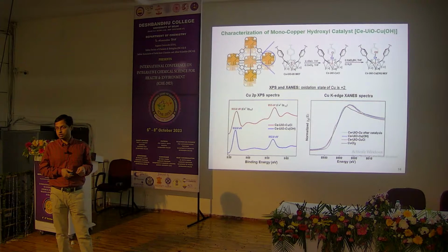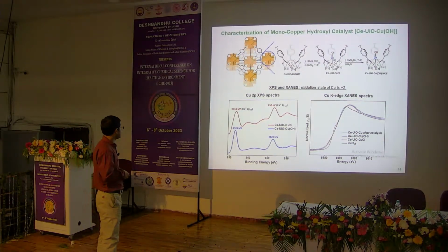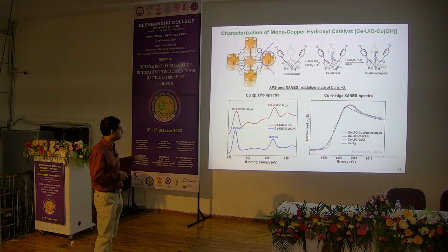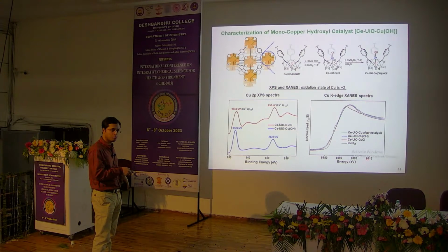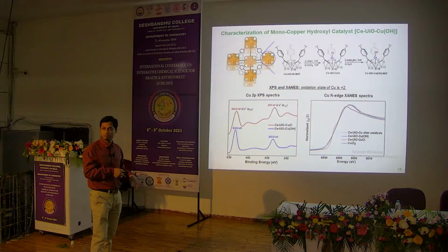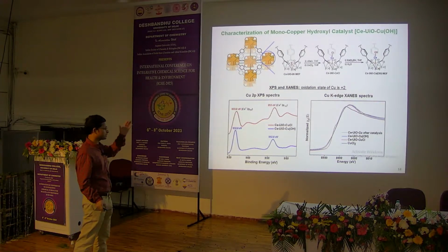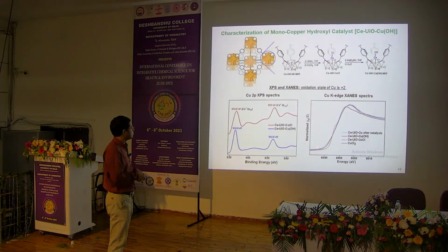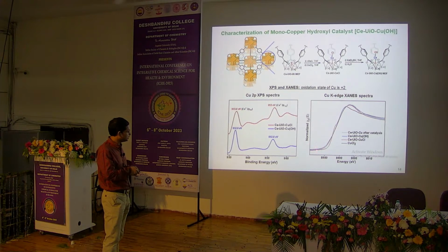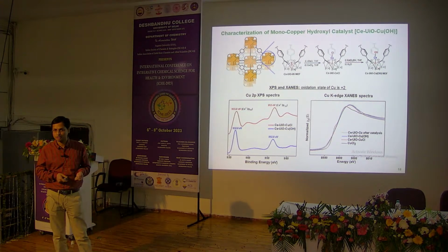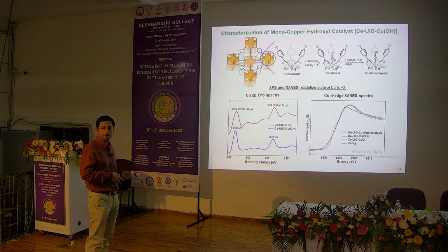The oxidation state of the metal center was determined by XPS, which is a surface technique, and XANES, which is the bulk analysis. For MSc students, if you don't know, it is X-ray absorption spectroscopy. In XANES, this is the beginning part, this is the K-edge of copper. Both XANES and XPS indicate that copper is in the +2 oxidation state in the MOF-supported copper hydroxyl catalyst.